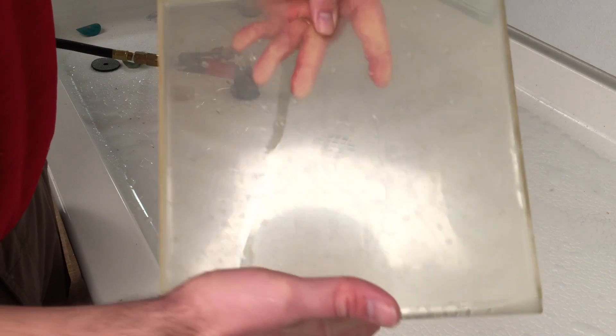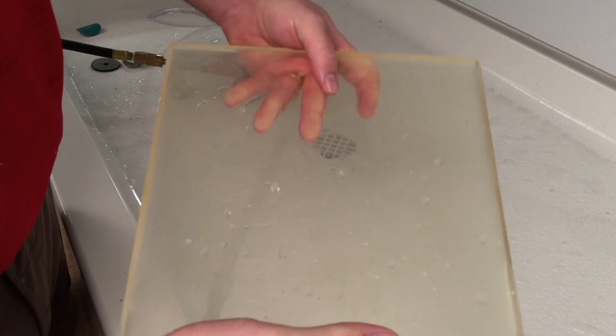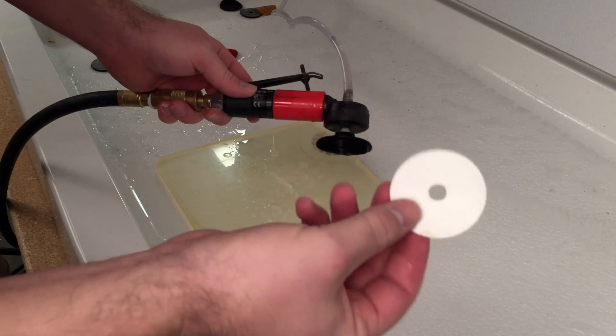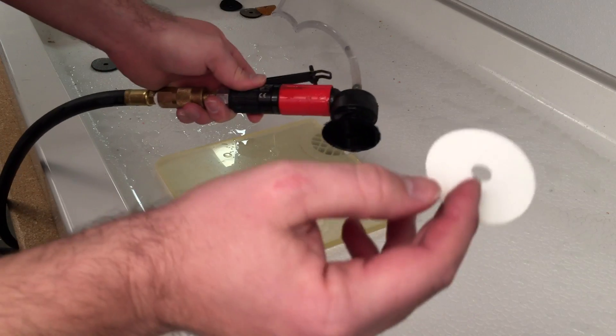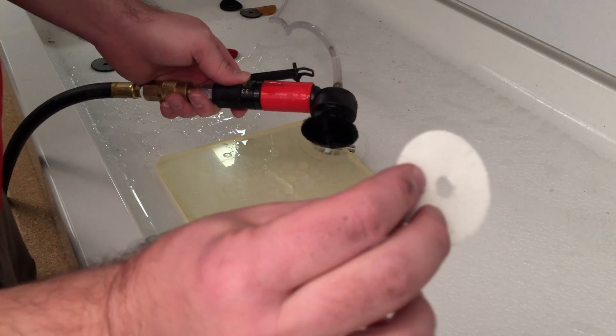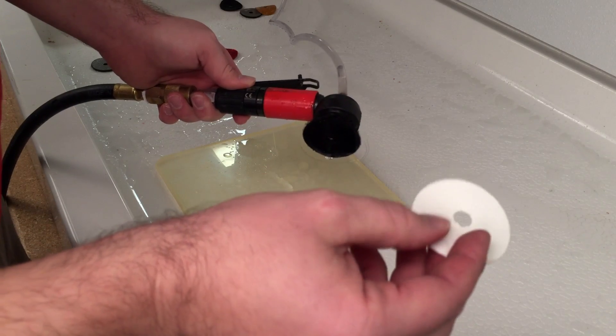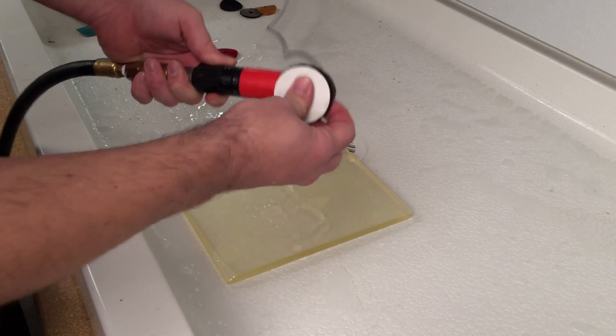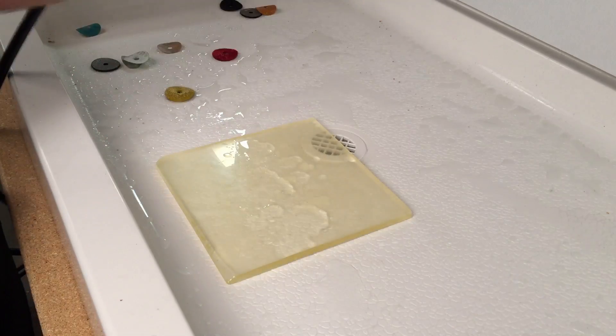You can take this, put it back into the kiln and slump it, and you're going to get a really nice surface out of this. You can fire polish it, or you can go all the way to a chemical polish with a cerium impregnated pad or a felt pad with cerium oxide. But that's looking really nice. Now, for polishing, one of the things we make is this 3M Cerium Impregnated Trizact material. It's great stuff. You don't have to use any cerium slurry with it. It's just Velcro back. Water activates the cerium on the surface. And it's got these little microscopic pyramids in here of the actual cerium. So the same process applies with this. Just Velcro's back on here. All you need is enough water on there to activate the cerium, and we'll get to town on this.